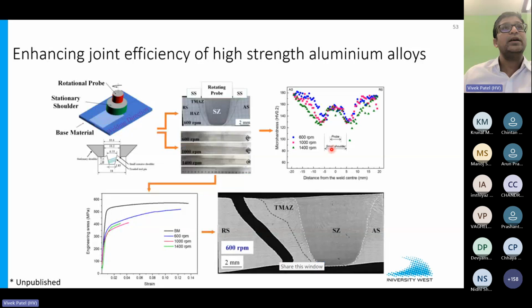Then we also worked on welding a butt joint of 7000 grade, 6 millimeter thick, 6.35 exact thickness. At that time we selected a stationary shoulder to minimize the distortion and to have a better temperature gradient from top to bottom. After tensile, we checked and found that the failure location happened away from the heat affected zone, and we got a tensile strength very similar to the parent material. So almost we got 90% joint strength of the 7000 grade of aluminum.